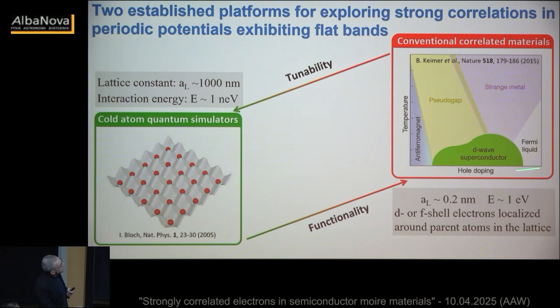Okay? So basically here you see the phase diagram of a cuprate. You see that it has many interesting phases as a function of temperature and hole doping. Okay? So this means that if you have no holes in the system, it's an antiferromagnet. It's interesting, but not very, well, maybe it's useful. I shouldn't say that it's not very useful. But basically, the interesting things happen as you start introducing hole doping. Okay, then you have this pseudogap, this strange metal tied to the d-wave superconductivity, etc.